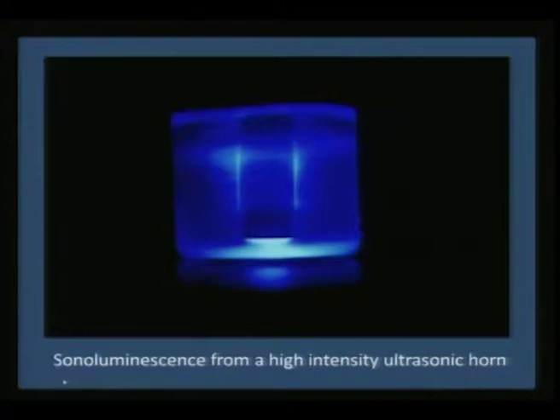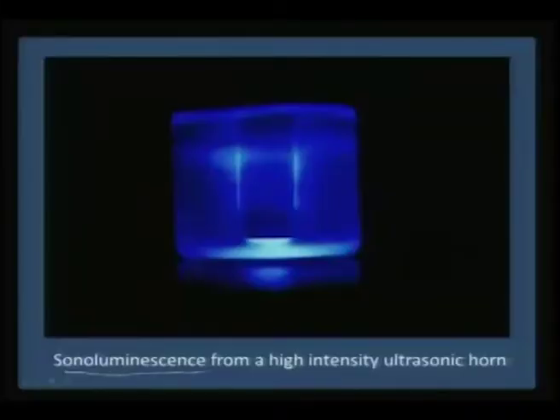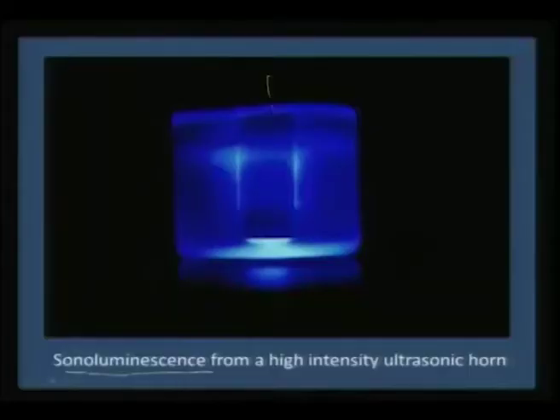Suppose you want to break some stones using ultrasound waves, you can rely on very high frequency ultrasound waves. But one of the very important manifestations of ultrasound which really brought material synthesis into focus is sonoluminescence. Suppose you are passing sound waves through a solution. If you can stabilize a single bubble, then you can actually see this bubble luminescing, which is called sonoluminescence. This is a typical cartoon of sonoluminescence. This is the titanium rod, and around it you see a bubble which is stabilized, showing luminescence.